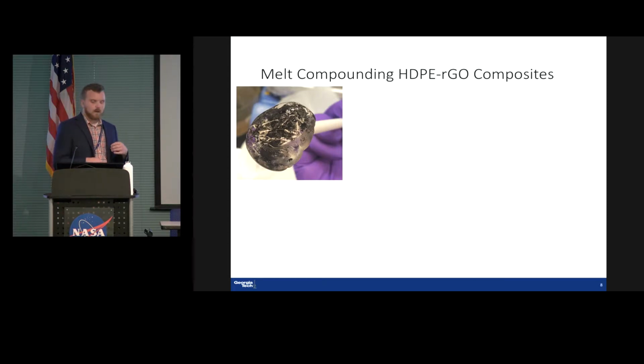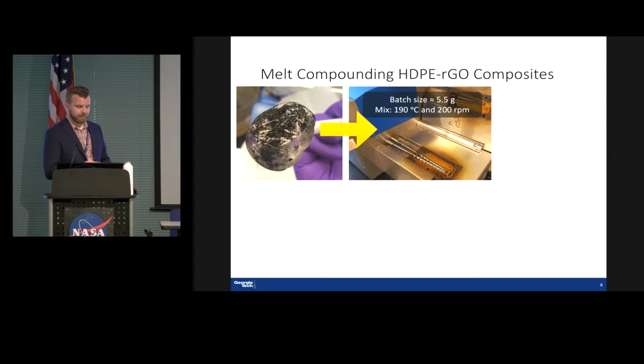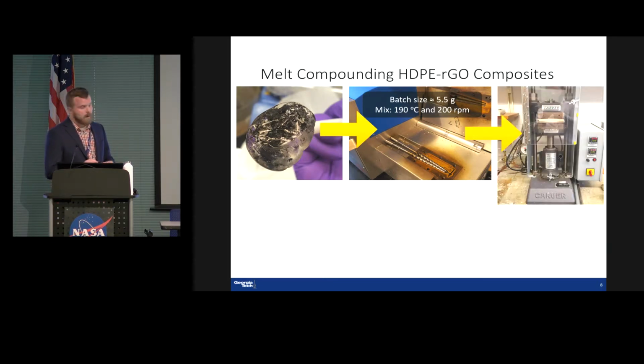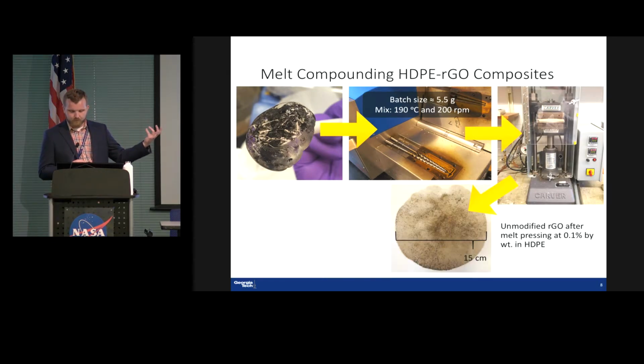So real quickly, I just want to walk you through what this process looks like in the lab. We start with the molten ball of polyethylene, and the large aggregates you can see, they're just stuck on the outside. They're not even well incorporated. We put them into an extruder that we can do about 5 to 6 grams per batch. We mix those at 190 degrees C. We put those in a melt press, and then we get these films, about the size of a pancake.